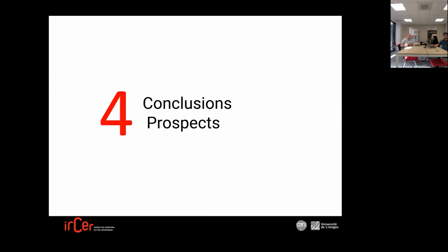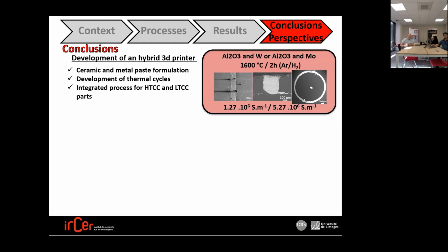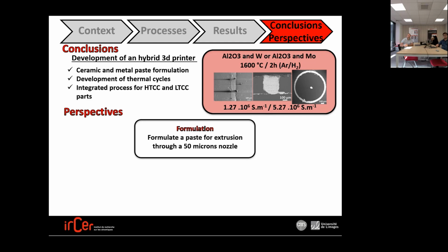So to conclude, we can see that a hybrid 3D printer able to make ceramic and metal in the same slice has been developed. We have developed then thermal cycles in order to sinter this part, and we can propose an integrated process for HTCC and LTCC parts. As perspective, we are now working on proposing better formulations, and the objective is to formulate a paste for extrusion through a 50-micron nozzle.